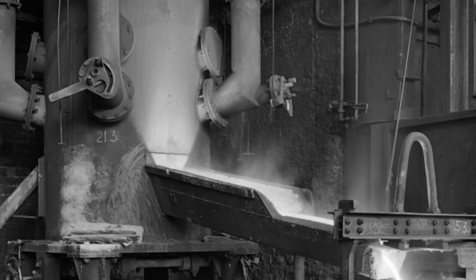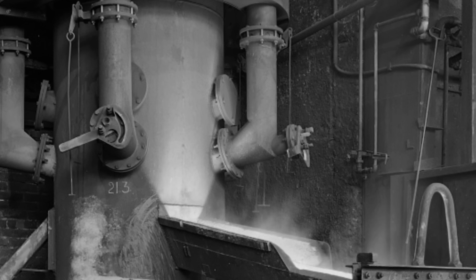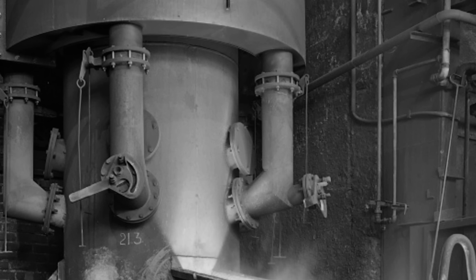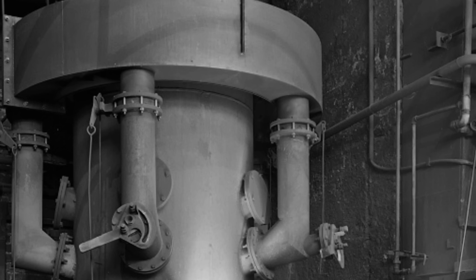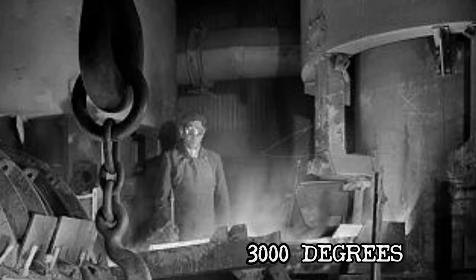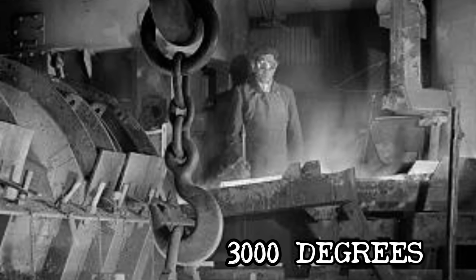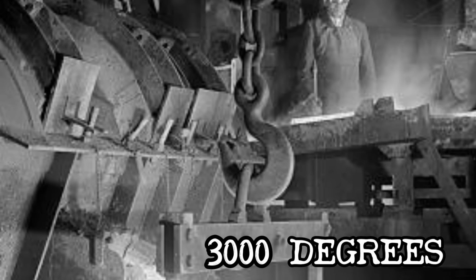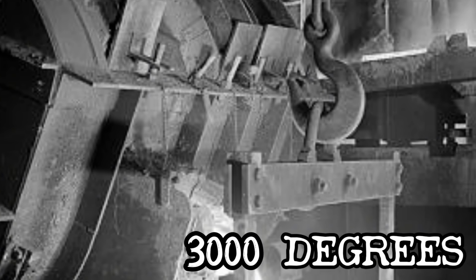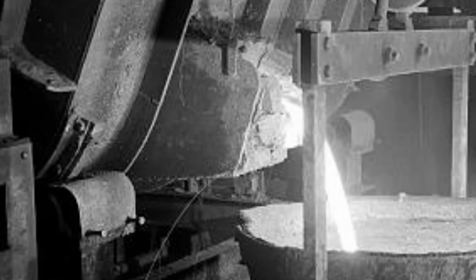You charge it from the top. Coke, limestone flux, scrap iron, pig iron, alloying metals, and you blast air through the tuyeres. The coke burns white hot, 3,000 degrees Fahrenheit, melting everything above it. The molten metal trickles down through the burning coke bed, absorbing carbon, picking up silicon and manganese from the additives, dripping into the well at the bottom as liquid steel. When the well fills, you tap it. Knock out the clay plug with a hammer and a pointed iron bar.